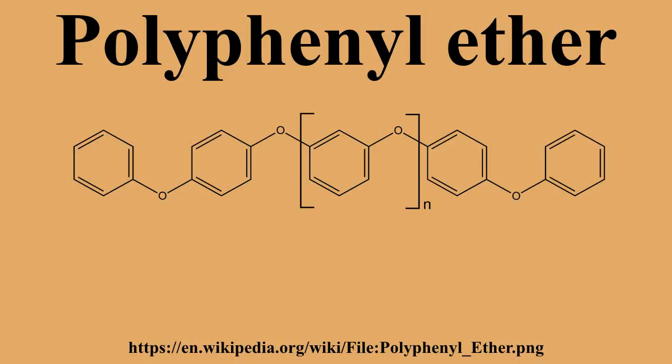Structure and synthesis. The proper name for a phenyl ether polymer is poly(phenyl ether) or polyphenyl polyether, but the name polyphenyl ether is widely accepted. Polyphenyl ethers are obtained by repeated application of the Ullmann ether synthesis: reaction of an alkali metal phenate with a halogenated benzene, catalyzed by copper. PPEs of up to 6 phenyl rings, both oxy and thio ethers, are commercially available.